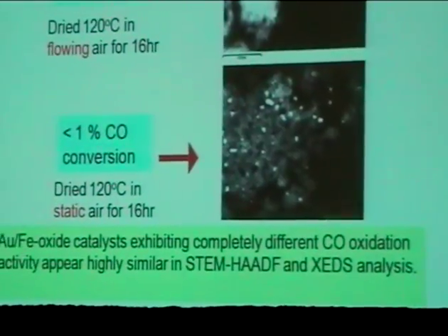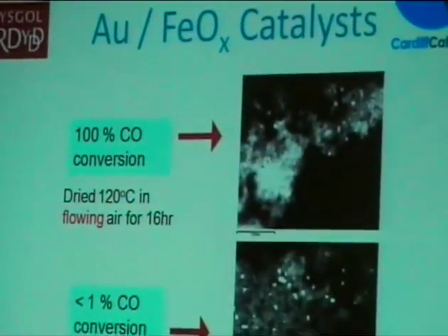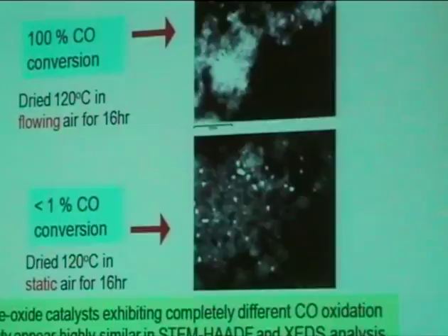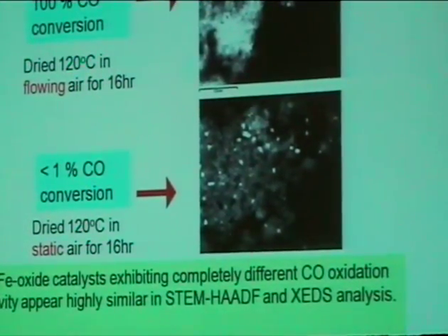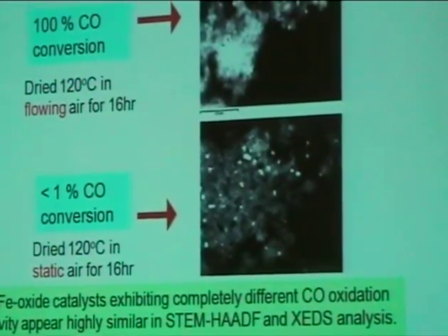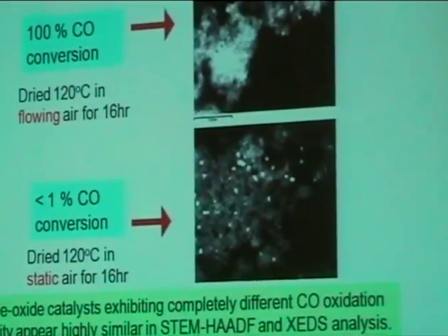The second sample was dried in static air at the same time at the same temperature, and this proved to be a very poor catalyst for CO oxidation. Through low magnification images, the catalysts looked very similar, indicating that the poor catalyst didn't have very, very large gold nanoparticles.